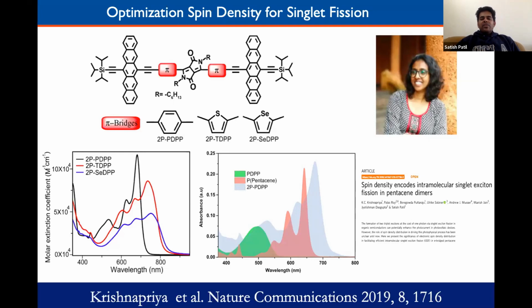We have not applied them for bulk heterojunction organic solar cells. The absorption here is indeed good, and I think that's a good idea to apply for bulk heterojunction solar cells. But in our work on bulk heterojunction solar cells, which I did not touch upon because of lack of time, we mainly use polymers because we want to make a printable ink. We want to print these solar cells for large applications. That's a separate research topic where we get very high efficiency now at IISc Bangalore. We get efficiency of 17 to 18% in our lab using a polymer based system, because the idea is that the number is good, but you want to print those things. If you start printing, then it makes a big impact on the technology.